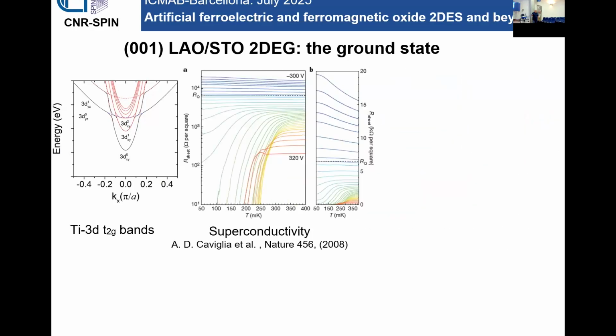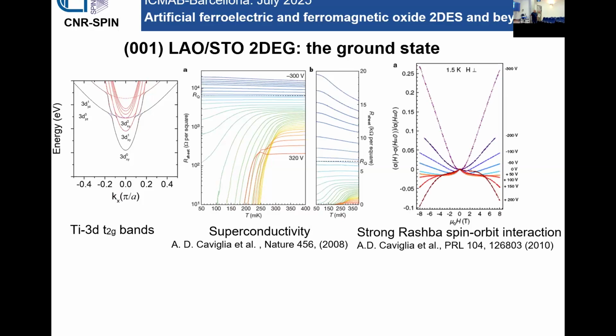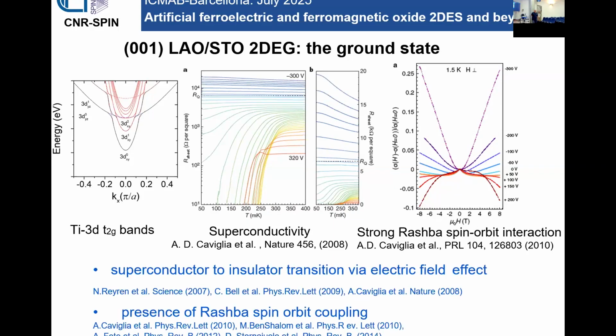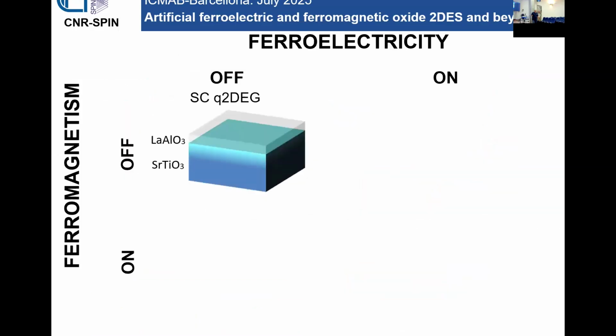But what is, from a functional point of view, maybe even more interesting is that superconductivity was already discovered in 2008, and it's possible with this system to get a full superconducting to insulating transition using the gate voltage. And not only that, this system features quite strong Rashba spin-orbit interaction, which was not completely expected, and which is also tunable. This is a magnetoconductance measurement, which is one way to study the contribution of spin-orbit coupling. So it's a system where you can have a superconducting to insulating transition with gate voltage and also tunable Rashba spin-orbit coupling. This is already a very interesting platform, for example, for spin-orbit qubits.